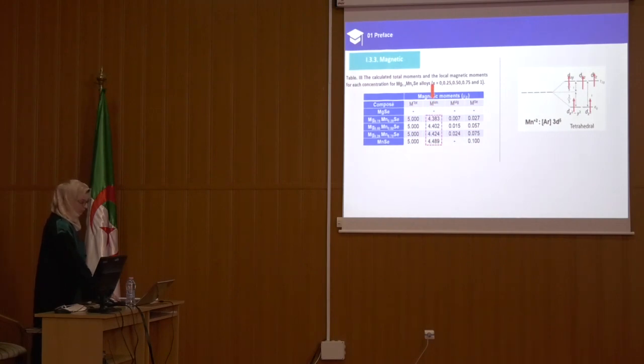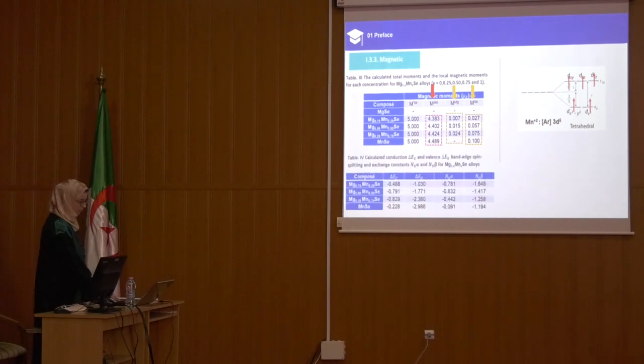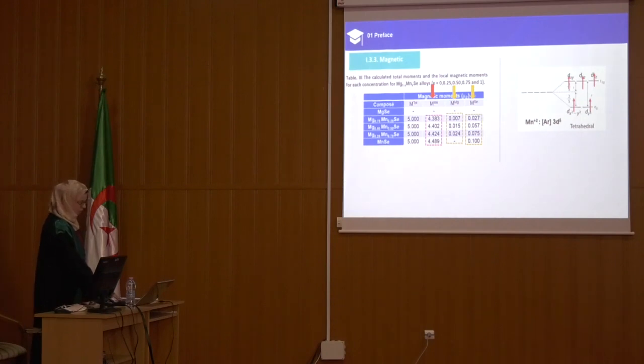due to the hybridization of the p-d exchange. On the other hand, a small contribution of local magnetic moment is induced on the non-magnetic Mg and Se sites. The negative sign